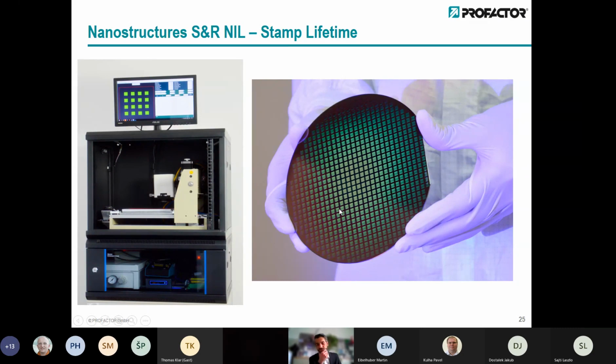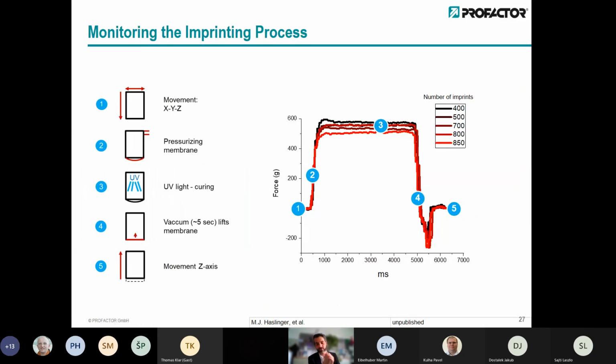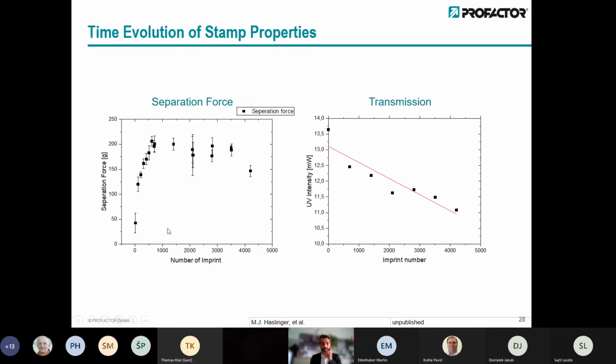This stepper was actually initially developed for material testing to evaluate the compatibility between stamp material and imprint material. And it has several features, so we can monitor the imprinting pressure and see how this evolves over time. For example, this is the force versus imprinting time during one imprinting step, and after 400 imprints, 700 imprints, and so on. And you can monitor if the stamp degrades or if the separation force changes, which is very helpful for process development.